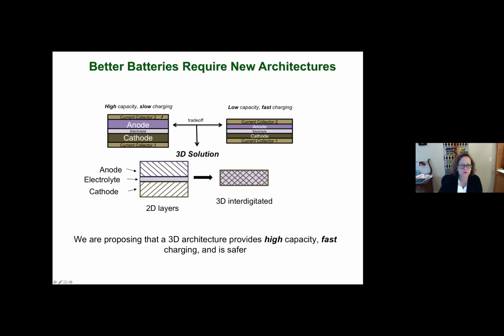Let's do this. So on the left here, I'm showing a battery that has high capacity, so thick layers. The trade-off then is if I want fast charging, so over here on the right, I have to make the layers thin. But what if instead we could interdigitate all the components? So the path length between the anode and the cathode at every point in the battery will be really short, but we can make use of the Z height of the battery to store a lot of energy. In that case, we propose that this architecture could give you high capacity and fast charging. And if you use the right materials and you eliminate flammable liquid electrodes or electrolytes, in theory, this battery should be really safe.